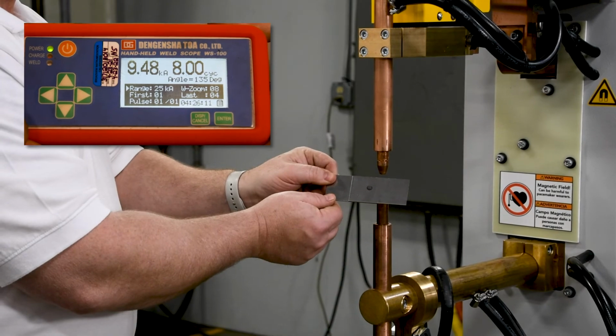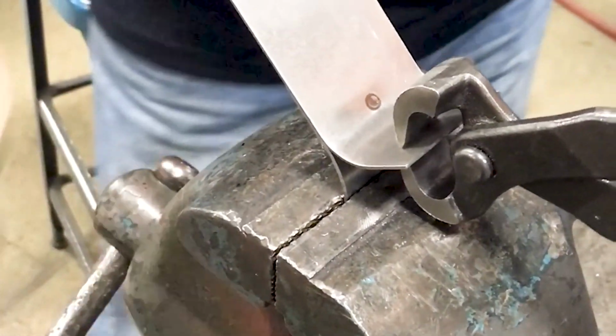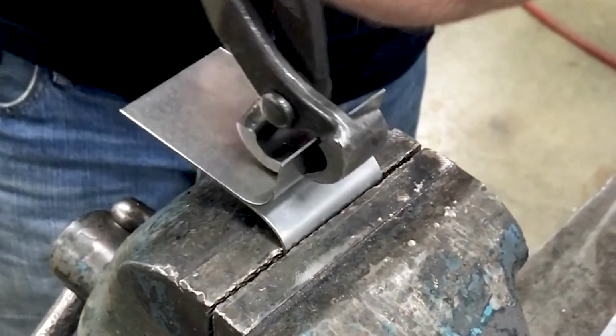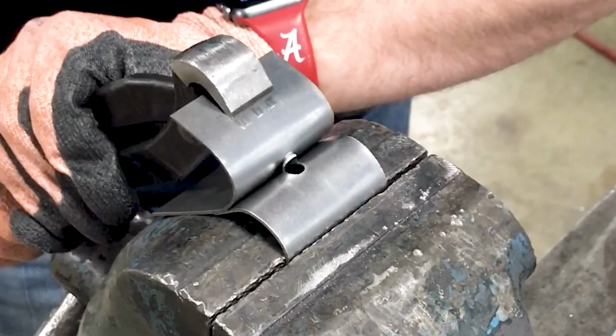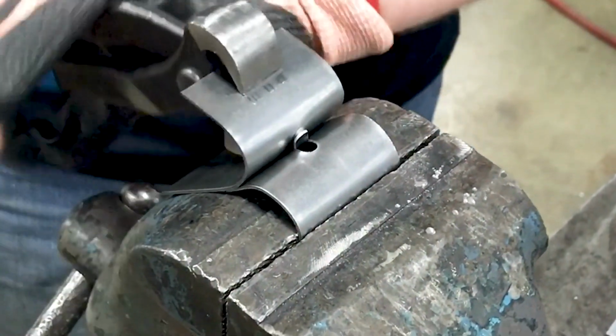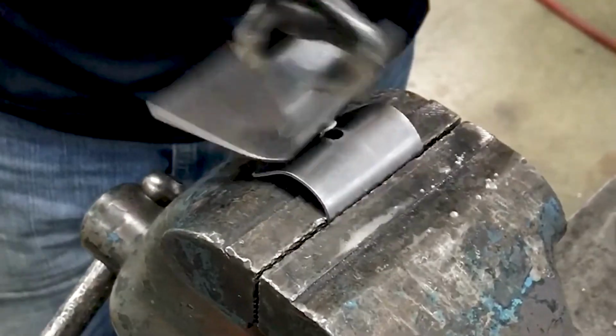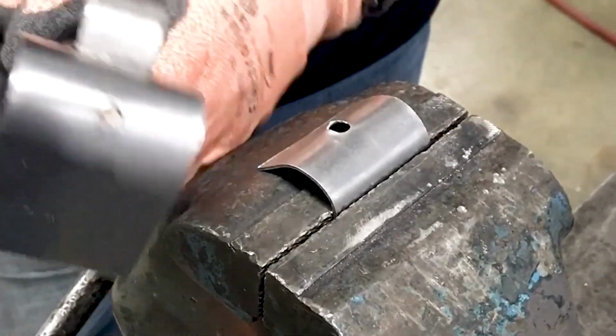Weld testing is usually accomplished by way of a peel test. The weld nugget should be around the same diameter as the weld electrode face. If no weld current meter is available, this test will be performed after each weld until reaching a satisfactory result. Upon achieving a good result, the squeeze time may be gradually reduced in the interest of speed of production. However, be careful not to reduce this value so low that force does not have an opportunity to reach the desired value before current is applied, which would result in material expulsion.